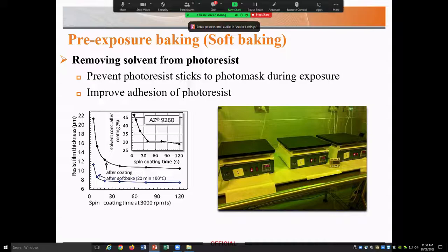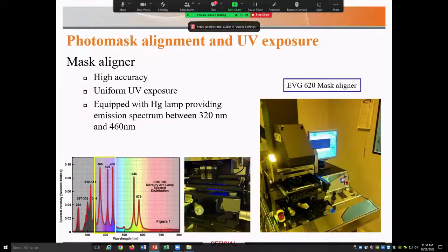So usually the concentration of solvent at the end of the spinning is around 10% for thin photoresist and around 35 to 40% for thicker photoresist. And then when we are doing soft baking at higher temperatures, the concentration decreases to 3 to 5%, which makes it ready to go through the exposure. So this is where all those chemical changes happen within the photoresist.